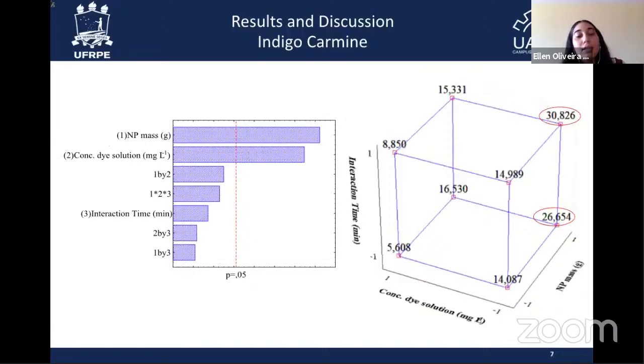As for Congo Red, the significant factors for the factorial design of adsorption of the indigo carmine were similar, only the mass of nanoparticles and concentration of dye solutions. In similar work carried out by our group, it was observed that there was no evidence of the significance of the time. And for this system of the interaction between nanoparticles and the indigo carmine, the higher percentages of adsorption were, as in Congo Red, test 2 and test 6, and as in Congo Red, we must privilege test 2, which is carried out with lower time, with less time.